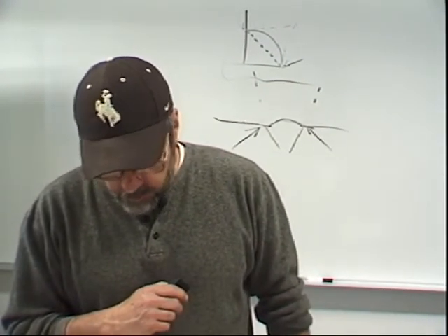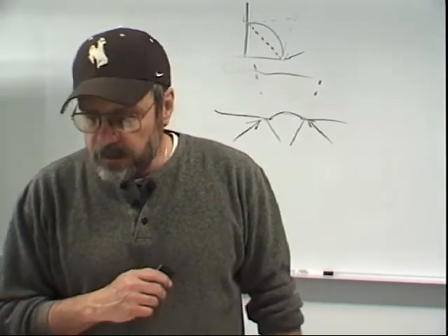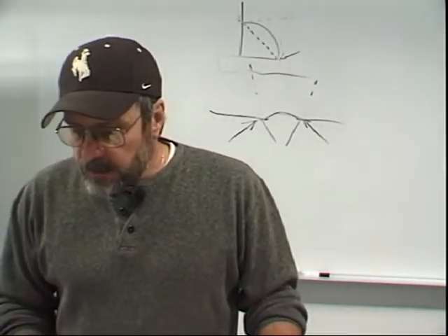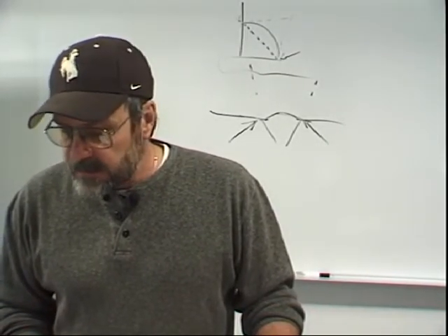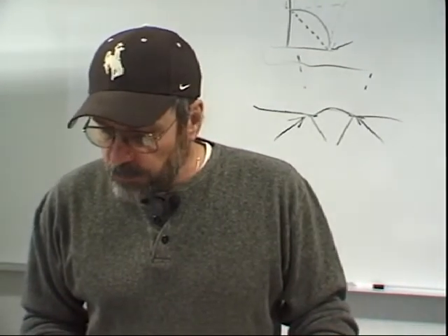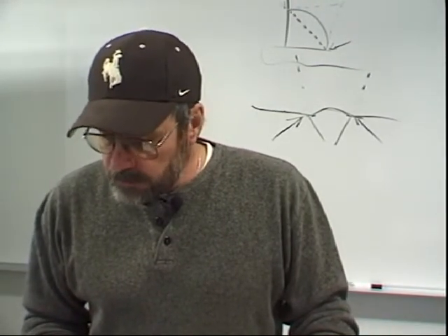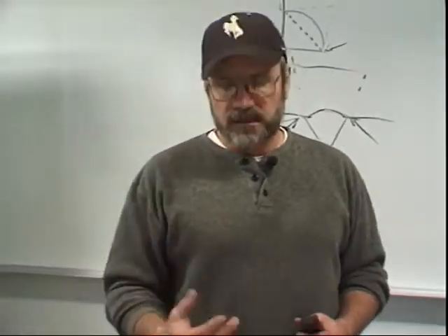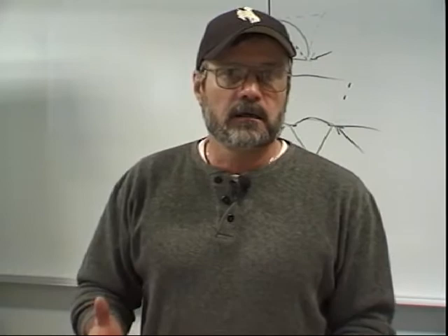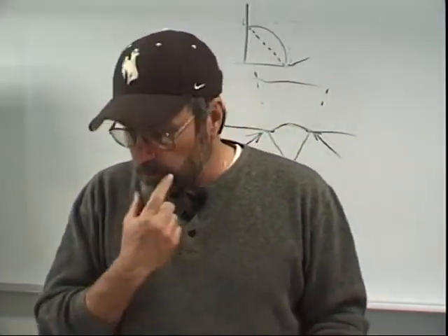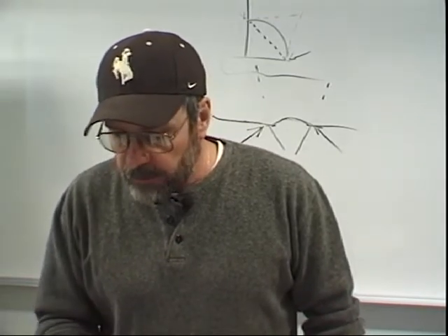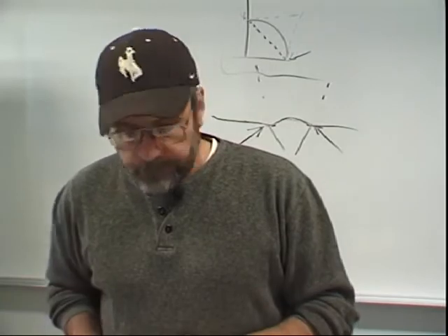So read about that. Over on page 923, in the second column, highlight the last paragraph where it reads, for the onset of lamellar tearing, three conditions must exist simultaneously. They are stress in the through thickness direction, susceptible joint configuration, and material having a high inclusion content, meaning there would be a lot of stringers in those things. And of course the through section, when we talked about the X, Y, and Z, Z was the through section direction, and that's what our picture showed there. And figure 9.45 shows the tearing in the through thickness section area.